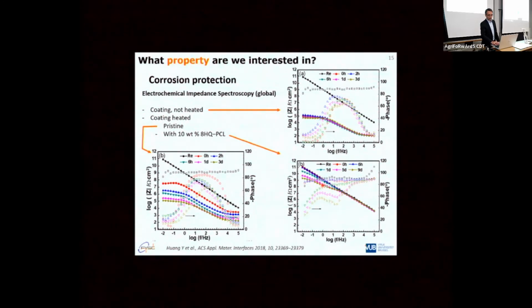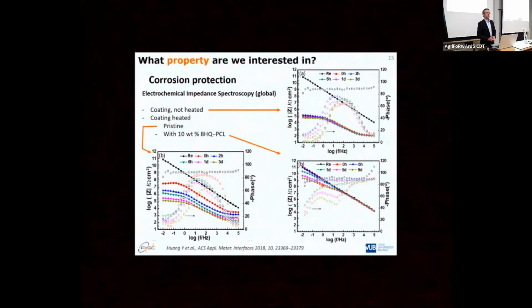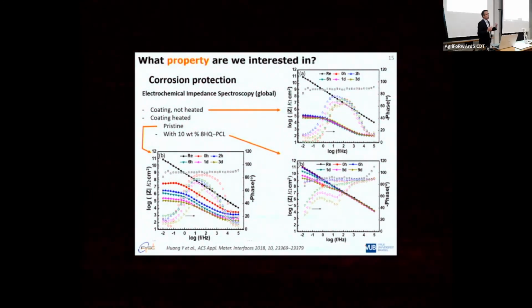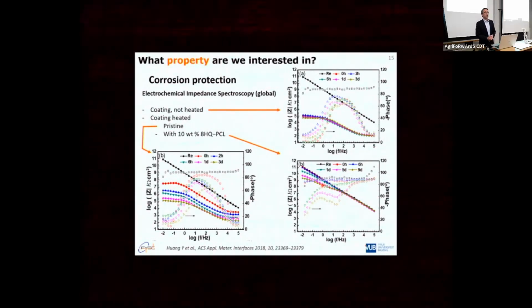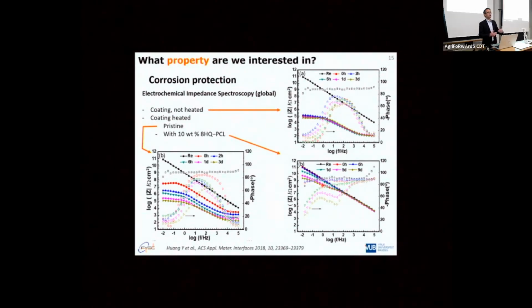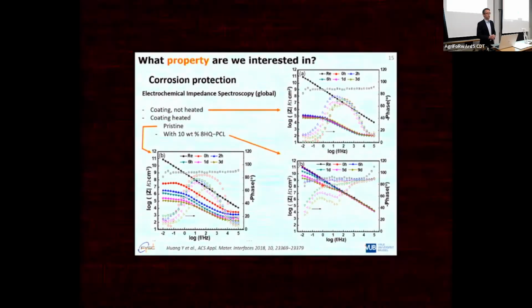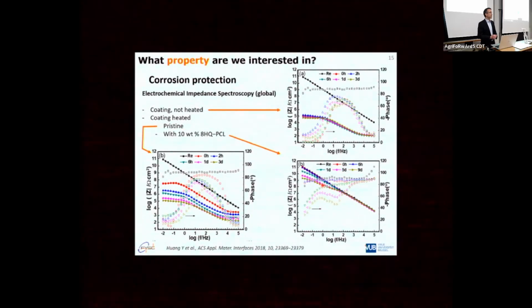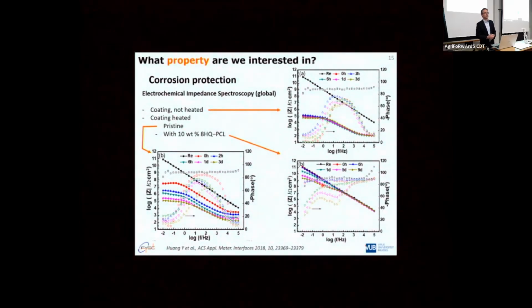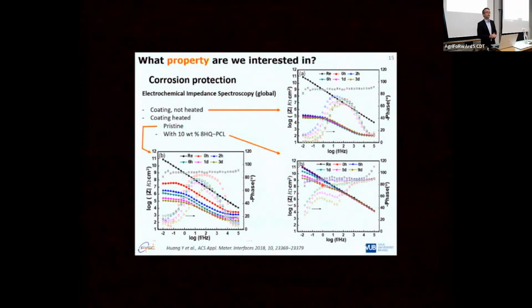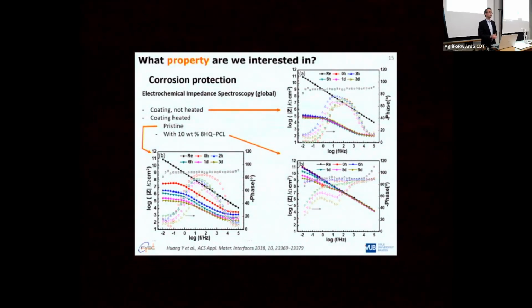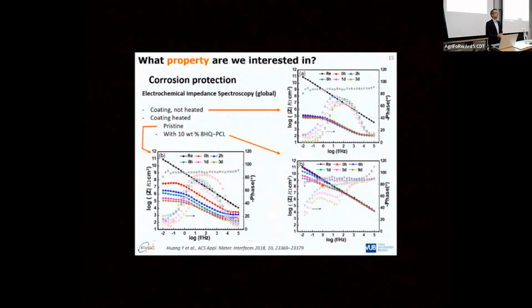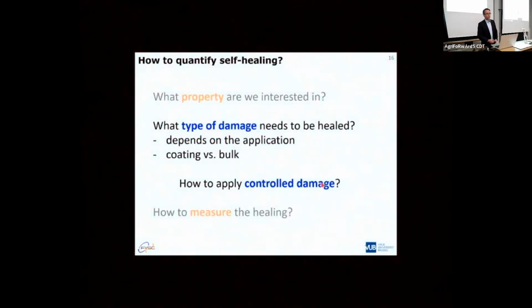Now, the next question is, how do we quantify it? Here, the answer could be, you look at the corrosion barrier properties of this layer and you use this as a measure for self-healing, but you could also look at the crack and the crack depth and see how that gets sealed and take that as a measure. Or you could study the mechanical properties of this coating and use those as a measure for self-healing. So you will need to choose which property you would like to follow.